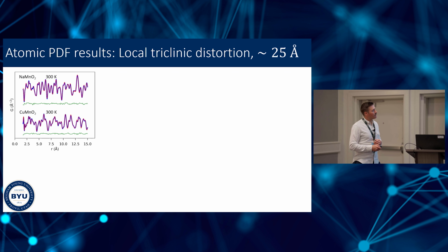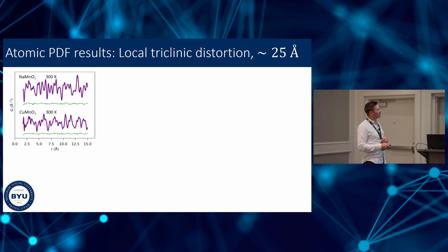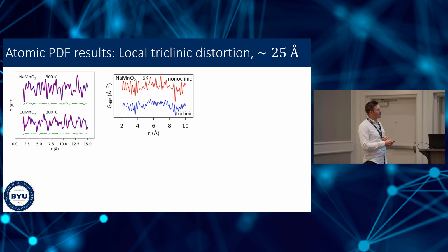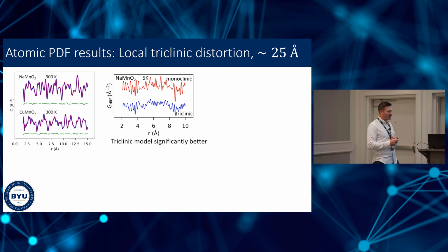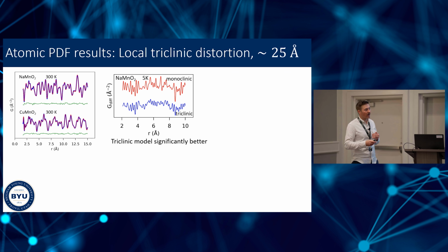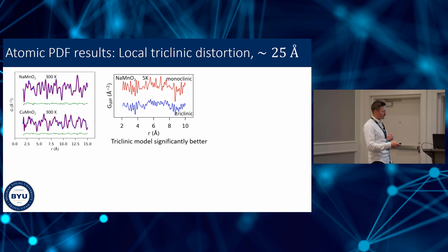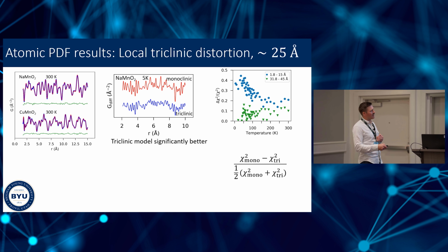Well, we looked at this with PDF analysis, and what we found was that the sodium manganese oxide compound at low temperature is better described by a distorted triclinic model rather than the long-range crystallographic monoclinic model. So this is just showing the fit residual. We've got smaller wiggles here for the triclinic model. So that means locally, sodium manganese oxide actually is triclinic, has this lower symmetry in the local structure. And we can look at the temperature dependence of that, and it turns out that this local triclinic distortion becomes more pronounced below about 150 or 200 Kelvin.